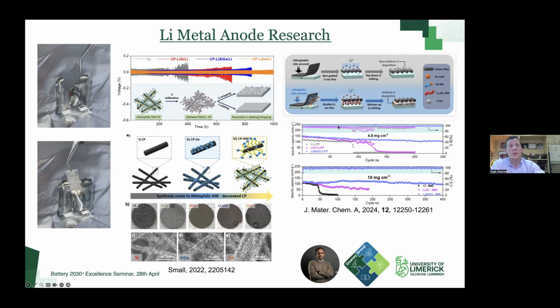And what you can see from the full cell performance that we have down here at the bottom is that this significantly increases the performance. So this is the blue one here with your lithophilic interlayer. The carbon cloth on its own, you can see that that dramatically drops off in terms of its capacity. And just based on a standard lithium counter electrode, that drops off much faster.